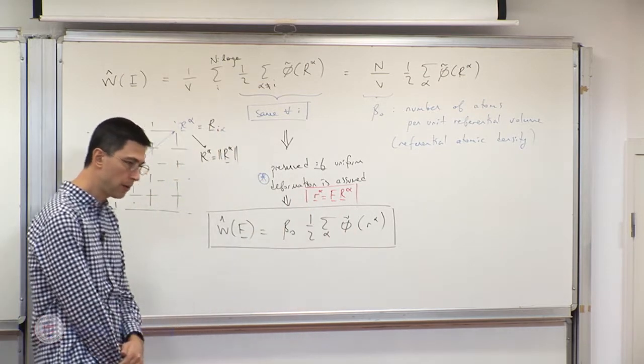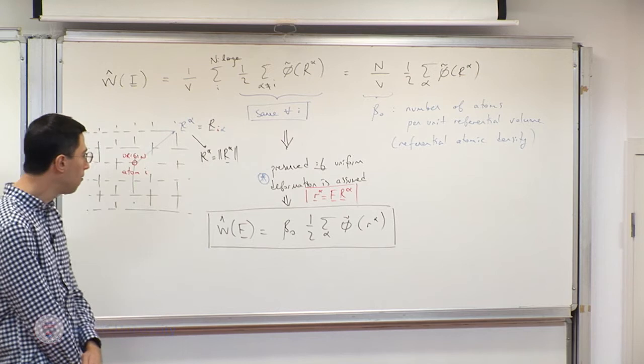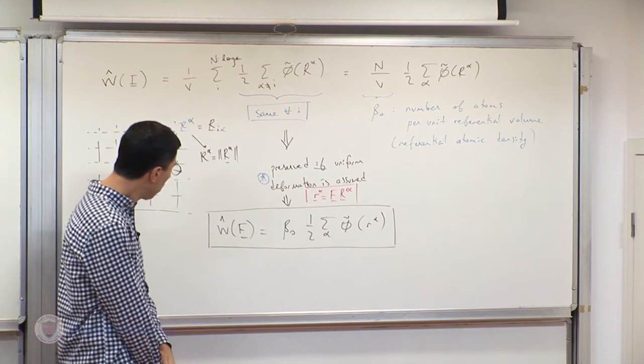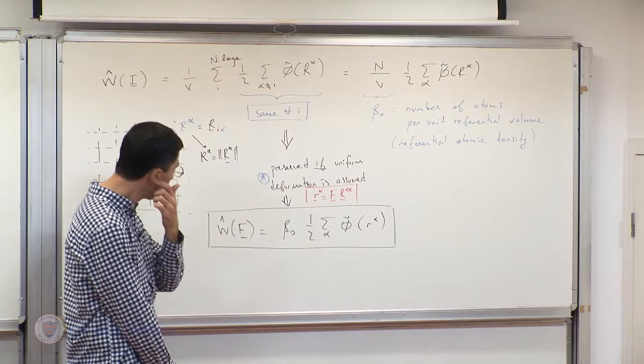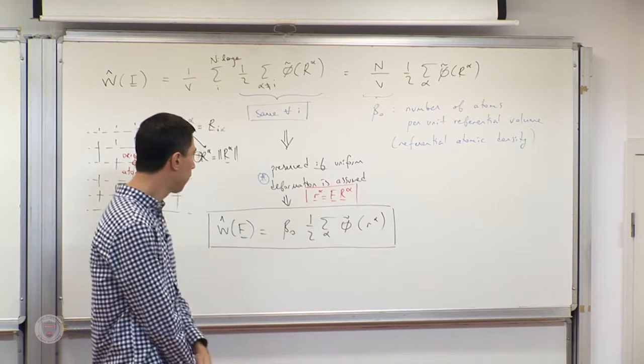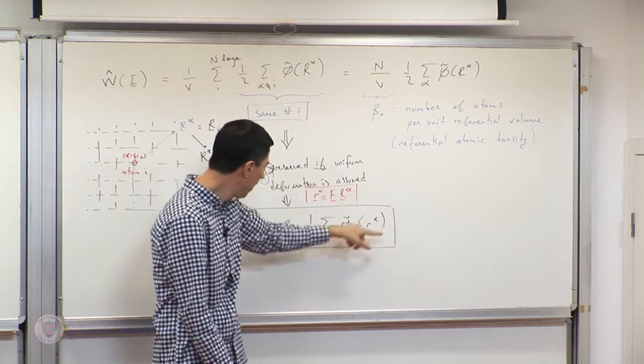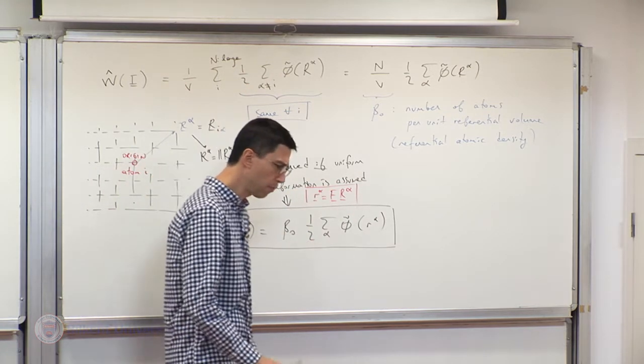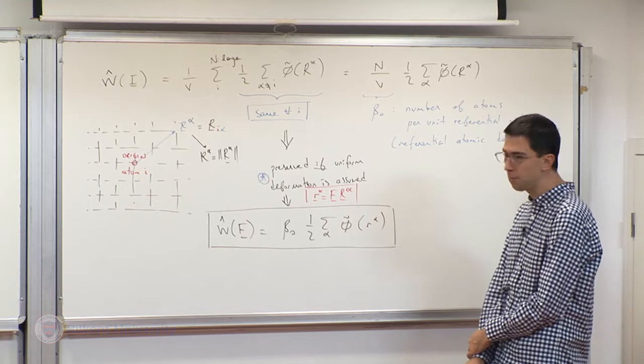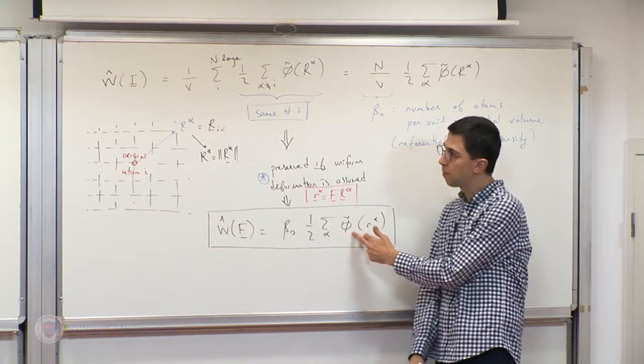We can proceed further and find the stiffness tensor from which we can extract elastic constants. There is an issue: I have assumed the crystal is huge, so this sum is over a very large number. But we know that phi-tilde decays to zero with distance — if atoms are very far away, there is no interaction between them.